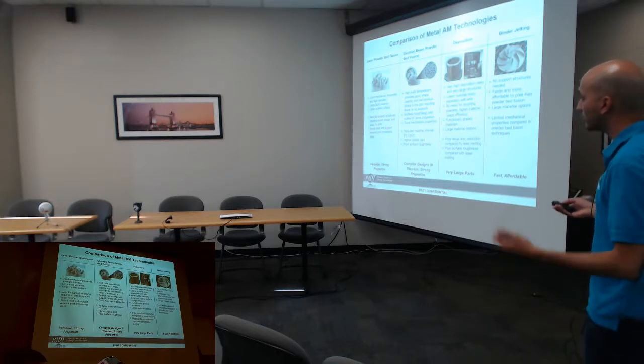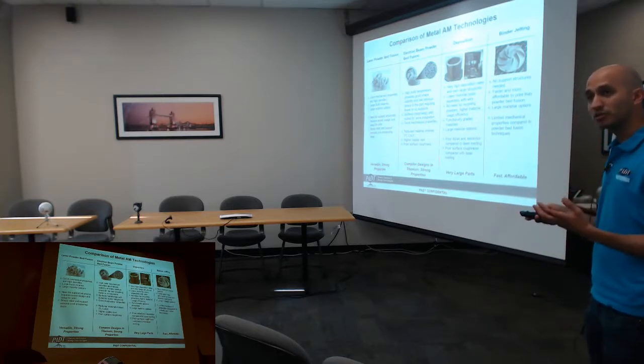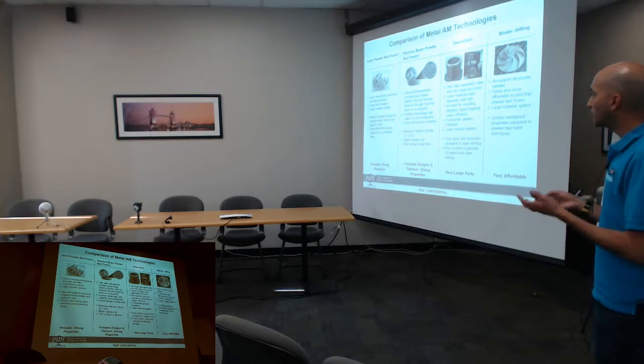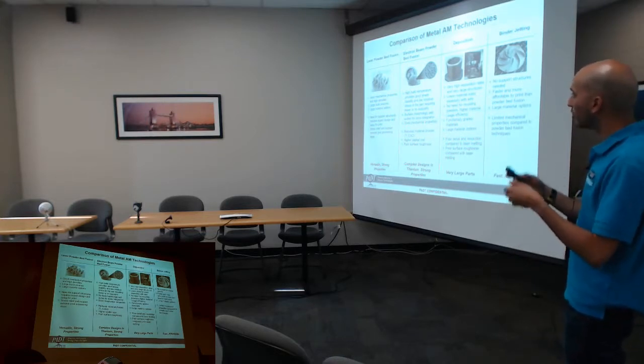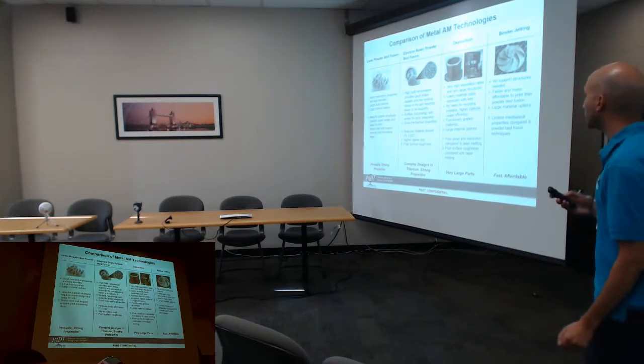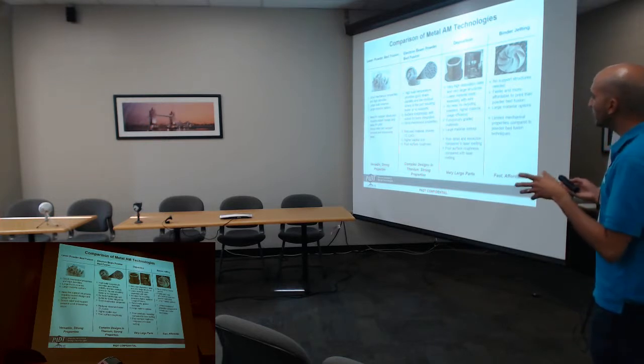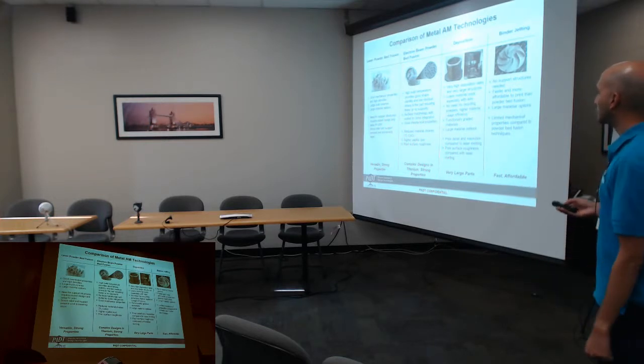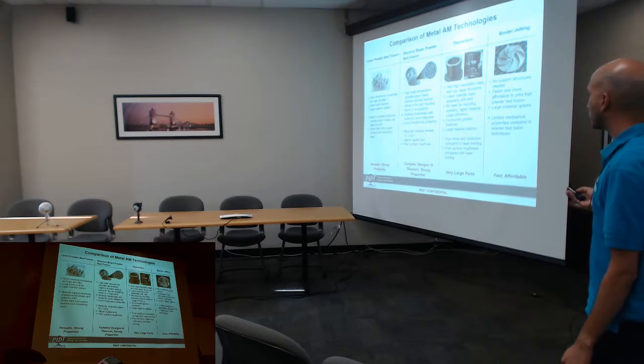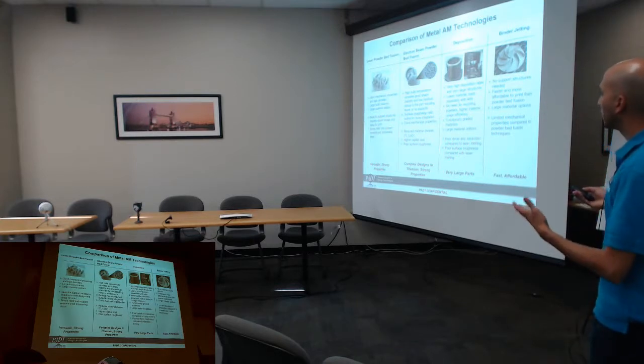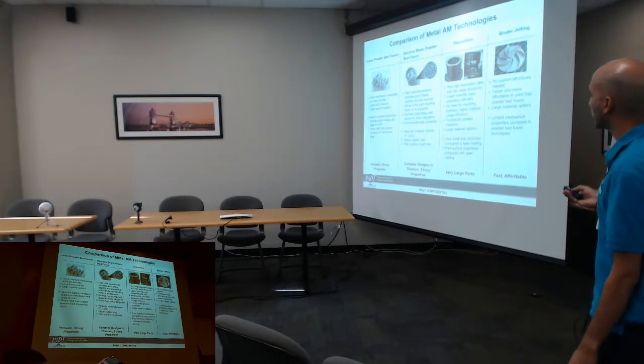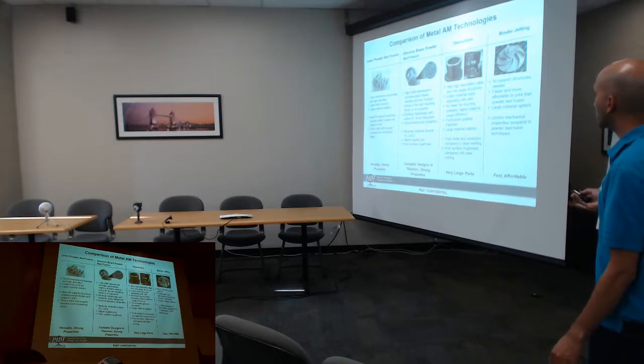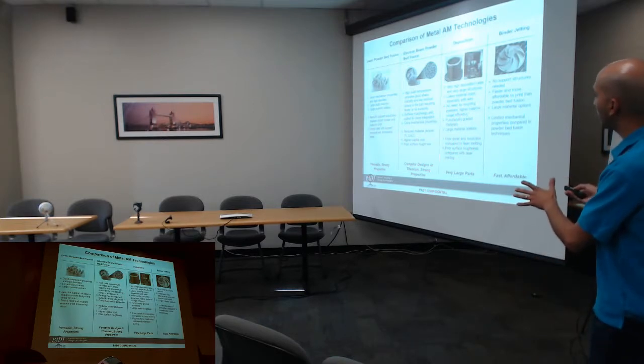Laser systems on the downside do need a lot of support structures, both for stress relief and, to a second order, for thermal dissipation. Electron beams primarily need them for thermal dissipation, not so much for stress relief. You typically get slightly lower residual stresses on electron beams. And so these two are fairly comparable in that sense.